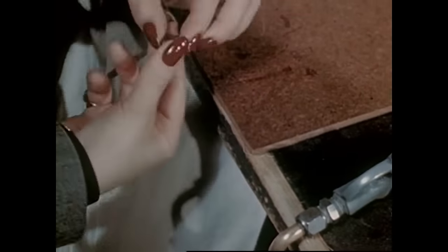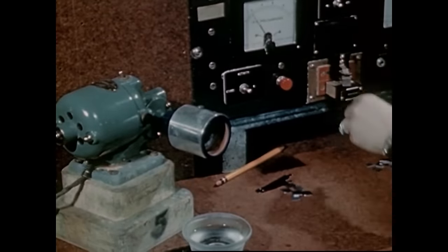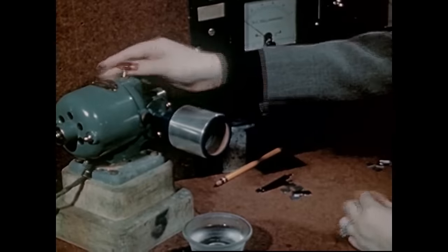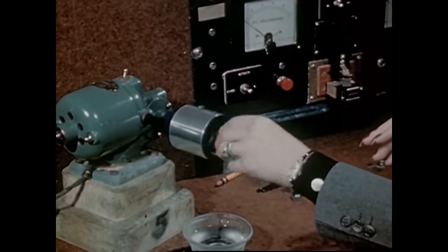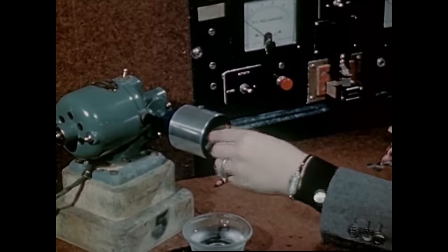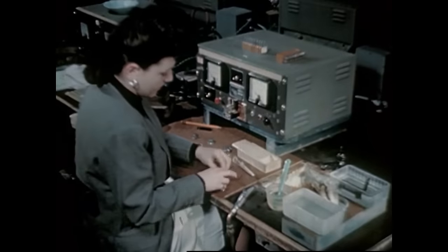and placed between electrodes. The crystal is then measured in the oscillator to determine the amount of frequency that must be etched off to reach the precise desired value. The activity of the crystal is also checked. In the instance seen, the crystal activity is found to be low. To increase the activity, the operator lightly laps the edges of the crystal by holding it within the abrasive-lined rotating drum.